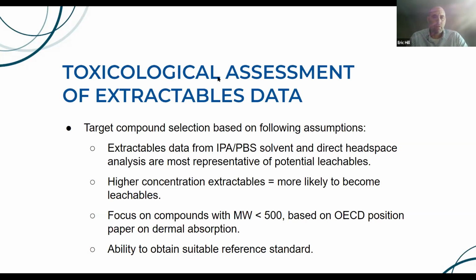We also focused on compounds with a molecular weight less than 500. And this is based on a position paper from the OECD regarding dermal absorption, that when it comes to dermal absorption, compounds with molecular weight lower than 500 are most likely to absorb versus ones above that are less likely to absorb. Doesn't mean they won't absorb, but again, when we're talking about coming up with a final target list from a large set of data, we use this assumption to help us come up with that focused list. And then we certainly wanted to make sure we chose targets that allowed us to obtain a suitable reference standard.